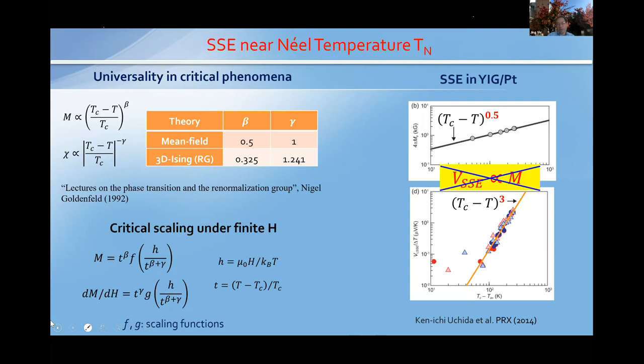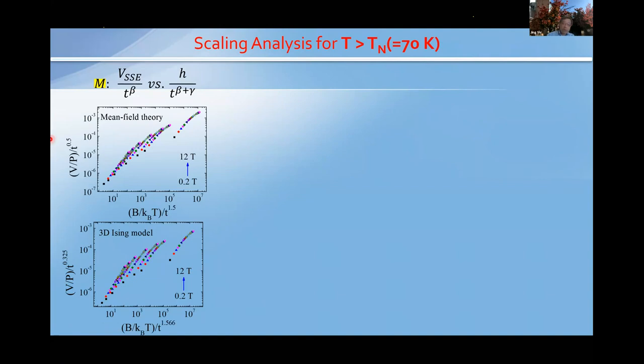Okay, as I mentioned, we tried M first. If we treat the spin Seebeck voltage as proportional to M, behaving like M, then first we try the mean field theory, where the exponents beta and gamma are one half, right? Then for this mean field, we do this standard scaling analysis. Clearly this doesn't work. Then we switch to 3D Ising exponents and do a similar thing, but with different exponents. Then clearly it doesn't work either.